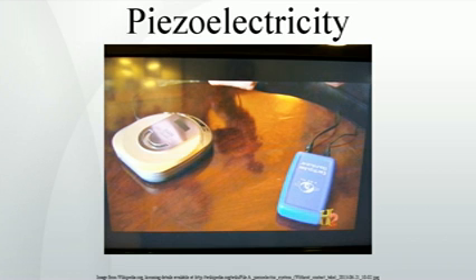In 2004, a group of Japanese researchers led by Yasuyoshi Saito discovered a sodium-potassium niobate composition with properties close to those of PZT, including a high Curie point. Certain compositions of this material have been shown to retain a high mechanical quality factor with increasing vibration levels, whereas the mechanical quality factor of hard PZT degrades in such conditions. This fact makes NKN a promising replacement for high-power resonance applications, such as piezoelectric transformers.